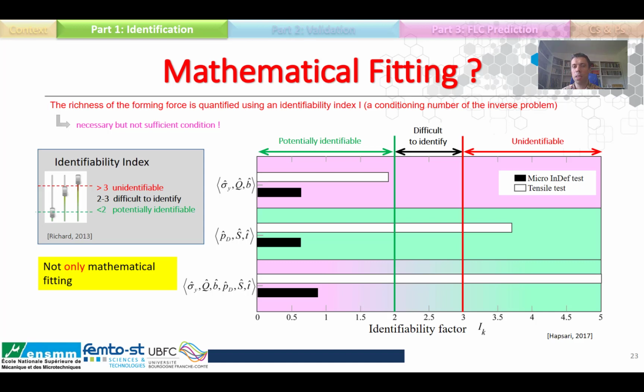Identifiability determines if there is enough information from forming force to identify the constitutive law. This criterion is based on the work of Richard. If the criterion is lower than 2, it means the parameters can be identified. If it's higher than 3, then they are unidentifiable.